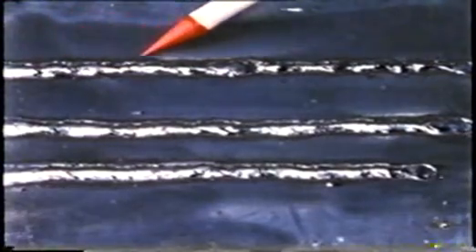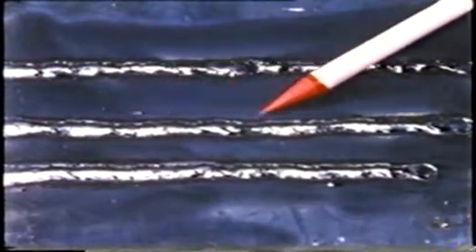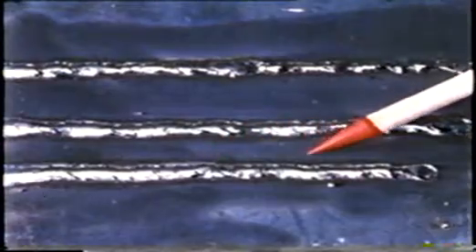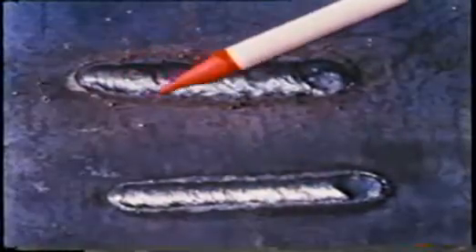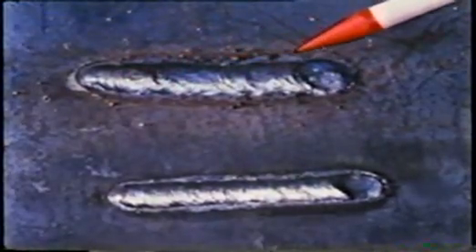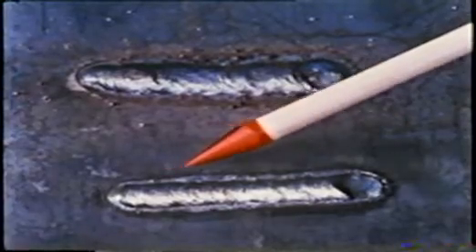Travel speed, which is too fast, is a common error with beginning welders. The weld bead usually is narrow with pointed ripples. On the other hand, if the travel is too slow, metal piles up excessively and overheats the base metal. Note how wide this bead is, as compared with our correctly run weld bead.